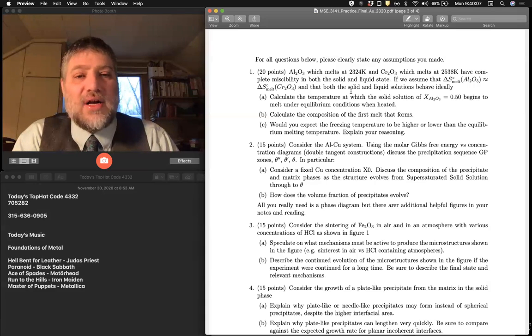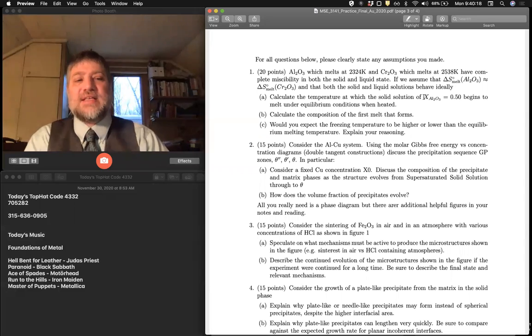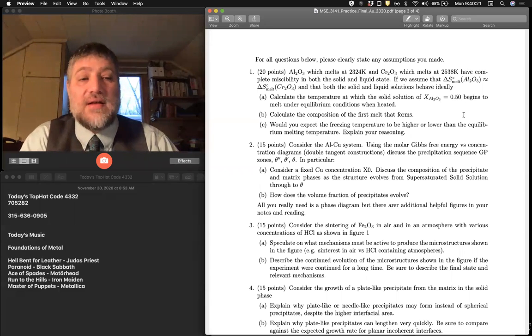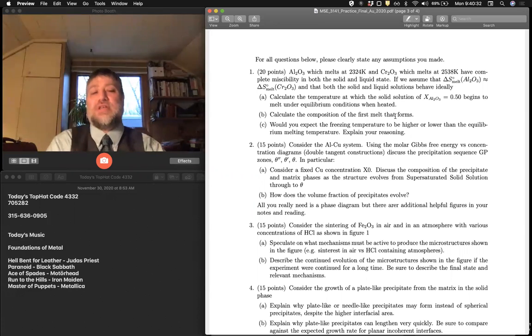And we're also going to assume that both the liquid and solid solutions are ideal, right? So if I have a mixture that's exactly 50-50, calculate the temperature at which the solid solution begins to melt, right? And then calculate the composition of the first melt that forms, right? So this is doing some phase diagram calculations, similar to stuff that was on the first exam, but again, much easier.